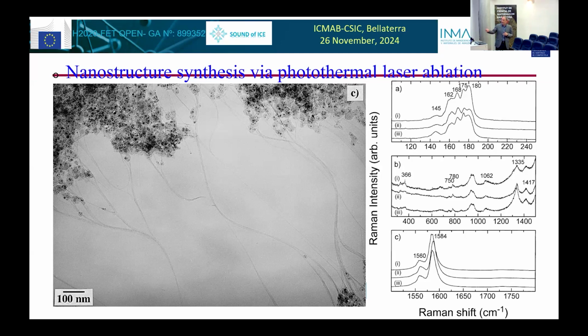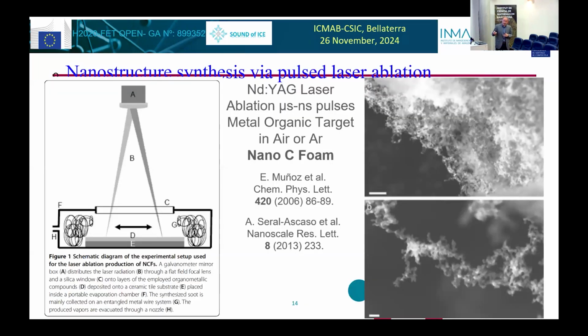We characterize this through Raman. I'm not going into the details, but this is well known, we have a paper extensively published on the Raman characterization, a specific paper with colleagues in Montpellier. We distinguish all these forms. So this was with a CO2 laser at 10.6 microns. When we go to 1 micron with a solid-state laser, an INMA-CSIC laser, also pulsed, then we found out that we did not get easily any nanotubes. What we got is another type of nanostructures, and these nanostructures were made up of an amorphous matrix and some graphenic type order structure embedded in them.